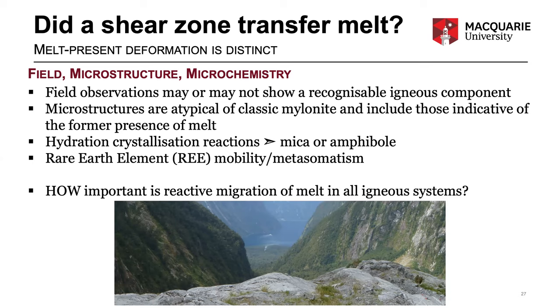We found that these are not typical of classic mylonite rocks and include microstructures that are indicative of the former presence of melt. An interesting point is that the observed melt pseudomorphs must crystallize at the end of the deformation story in order to be preserved in the rock. This implies that once the melt crystallizes in our shear zones, the shear zone and the rock become hard, such that those delicate melt pseudomorph microstructures are preserved through to today.